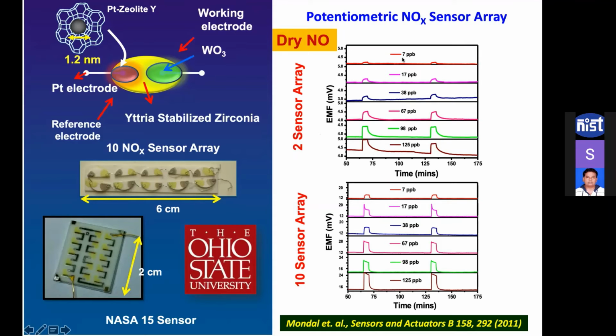Even for a very low concentration of nitric oxide, 7 parts per billion, we get a sensor response, but it is very, very small. The response is 0.2 millivolt. For a 10 sensor array, the signal improves to 10 times that of the two sensor array. So as this kind of sensor is very sensitive, we can detect 7 parts per billion. So we can use this kind of sensor for breath monitoring applications.